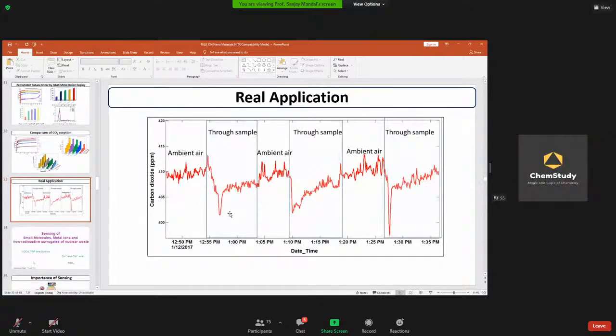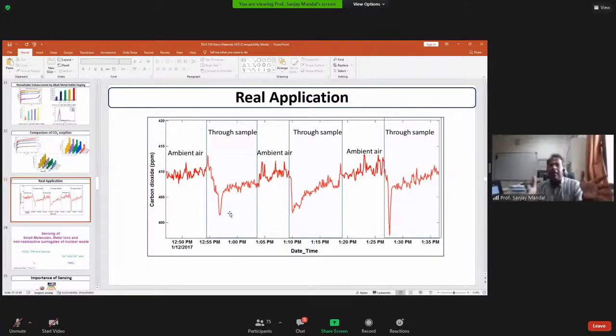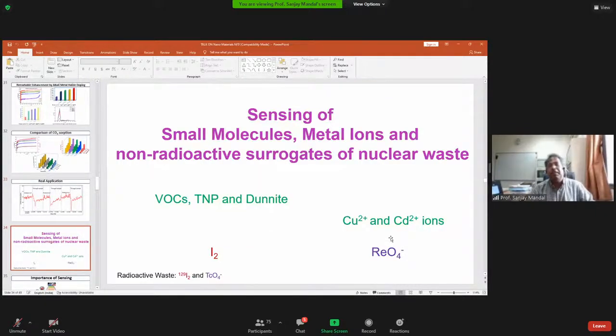And here's the real application. What is the real application? We took this material and passed ambient air through it. In IISER Mohali in 2017, this was about 412 ppm of CO2, and when we pass it through, it goes to 402. Then we did this 3 times, and we can lower it to below 398 ppm of CO2 using our material at room temperature, in the presence of water and all of that.